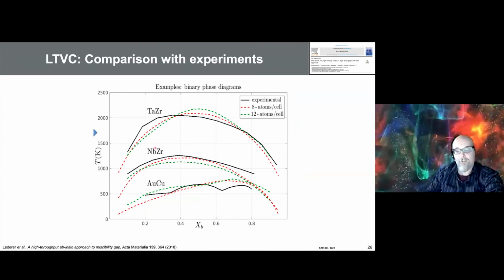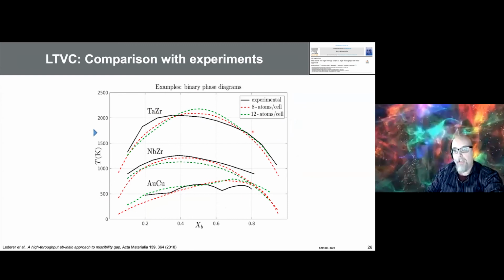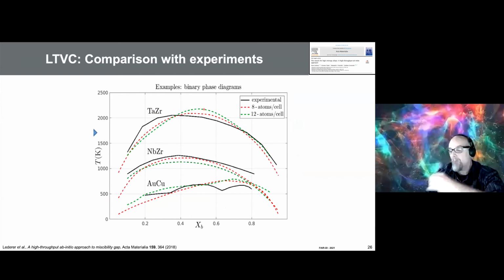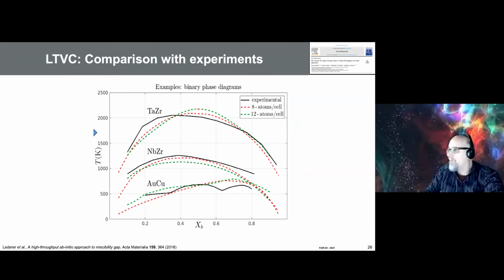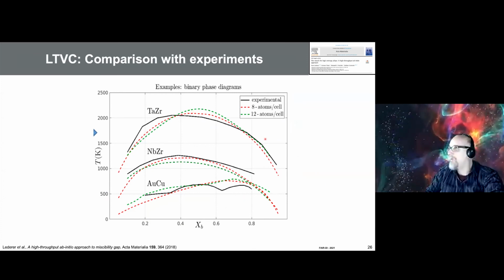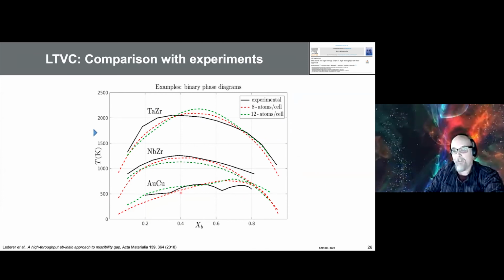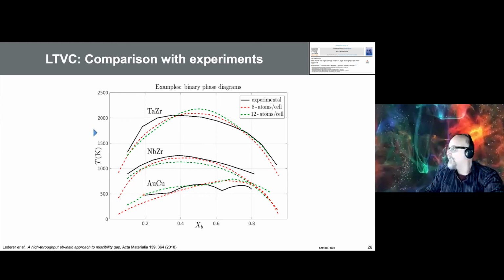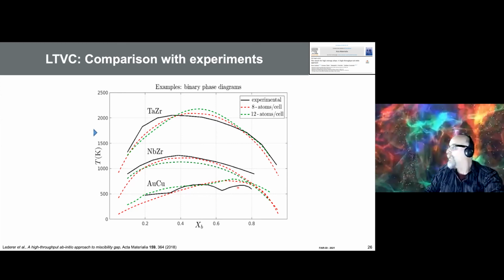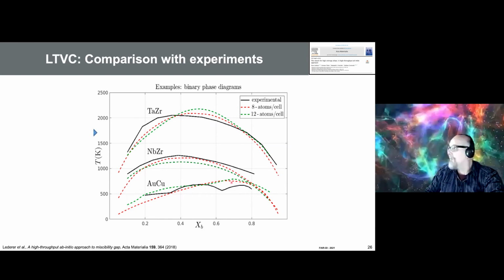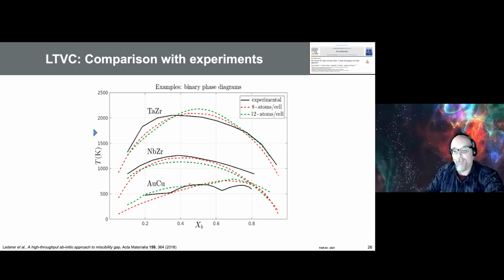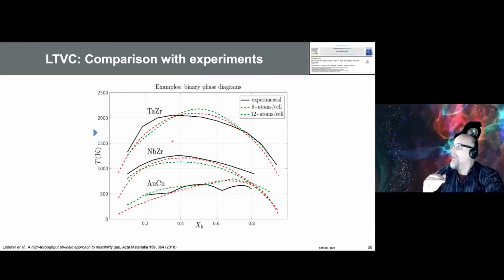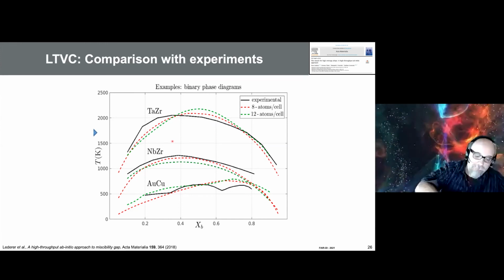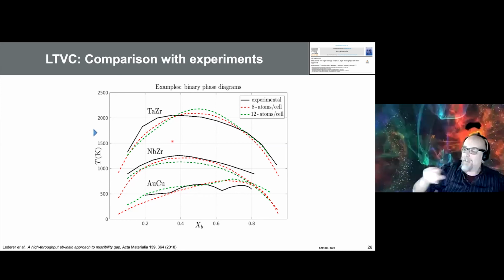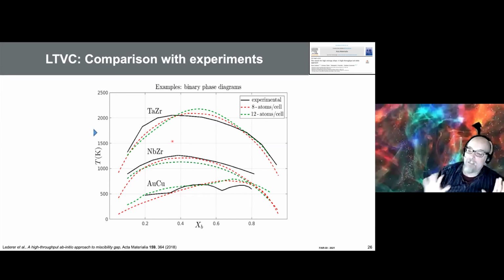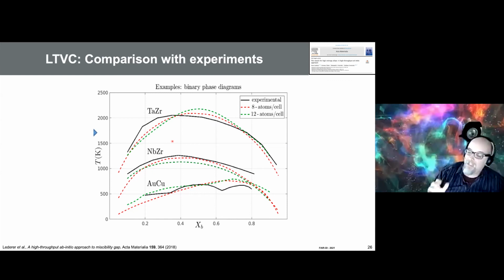This is for tantalum zirconium, for niobium zirconium, for copper gold. Look, our calculations, which take weeks, are those, and this miscibility gap can take years. Think about the miscibility gap of copper gold. After hundreds of years it has not really been found well, because at low temperature these quantities are very hard to find. Anyway, once you have the miscibility gap and you have the machinery to get to the melting point, then you are done. You really have the low part of the phase diagrams and the high part of the phase diagrams, and you're already exploring phase diagrams with big data.